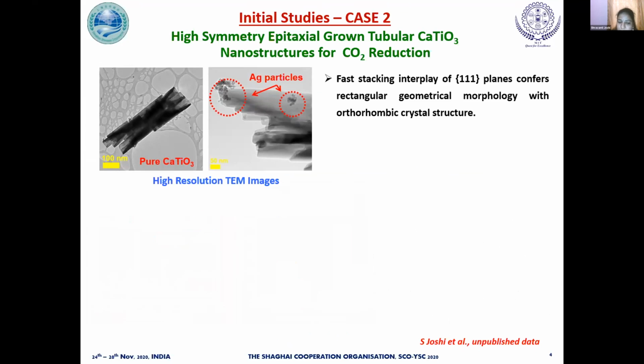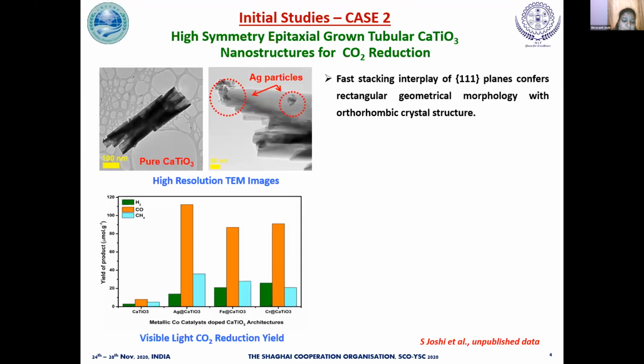Now here if you see, compared to the doping which we have used, that is silver, iron, and chromium, with silver nanoparticles we managed to get very good photocatalytic CO2 conversion rates. Further, the three-dimensional nano-architecture structure enabled more light harvesting activity.